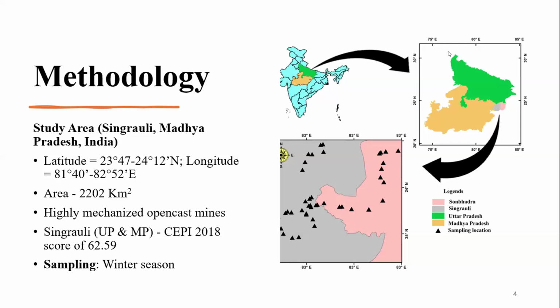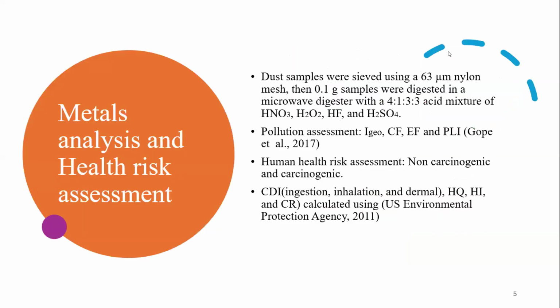The sampling was done in the winter season. The street dust is collected nearby the street and taken to the lab. Then the sample is sieved using a 63 micron nylon mesh. Then the sample is digested using a mixture of acids: nitric acid, hydrogen peroxide, hydrofluoric acid, and sulfuric acid in the ratio of 4:1:3:3. After that, the sample is filtered and analyzed in ICP-OES. After that, we calculated the metal pollution indices, that is the geoaccumulation index, contamination factor, enrichment factor, and pollution load index according to the standard formula.